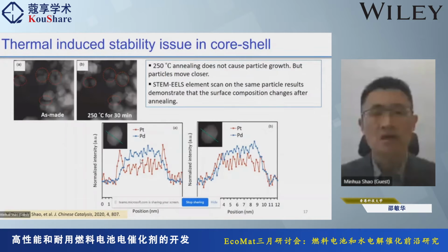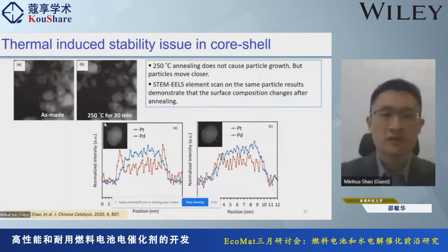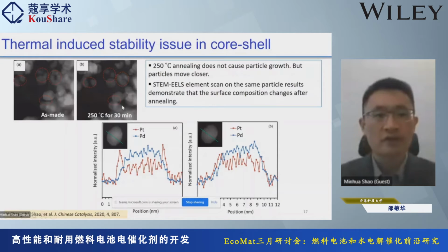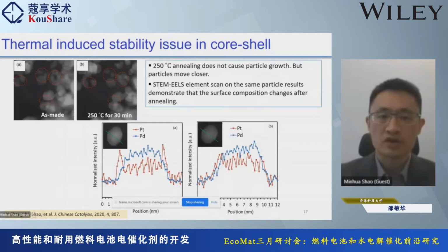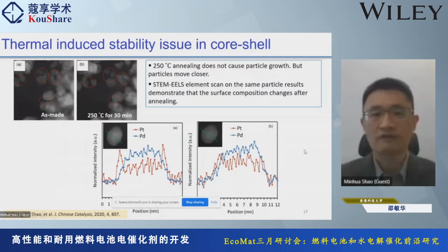So we did this study using in situ TEM at different temperatures. We can see that at 250 Celsius, we started to see some of the particles migrate closer, but there's no growing. The particles are still separate; they are not growing into one single particle. Then we did the STEM EDS correlation on the same single particle, before and after heat treatment. After heat treatment, there's a mixing of the palladium and the platinum. Initially you have very sharp peaks, so the core shell is very clear, but after heat treatment at 250 degrees C, you already see the mixture.